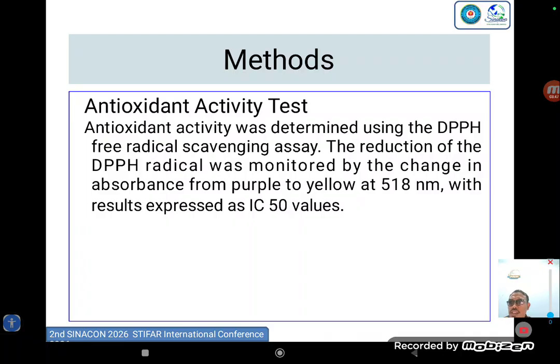Antioxidant activity was determined using the DPPH free radical scavenging assay. The reduction of the DPPH radical was monitored by the change in absorbance from purple to yellow at 518 nanometers, with results expressed as IC50 values.